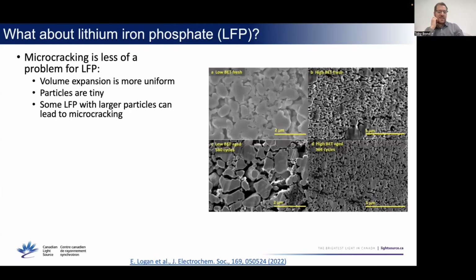Okay, and then one last slide, because I mentioned I would come back to lithium iron phosphate. Is microcracking a problem in LFP? Not as much is kind of the short answer. This is because that volume expansion I mentioned still happens, but it's more uniform, and the particles in LFP are tiny. This is some research by a lab mate of mine, Eric Logan, who looked at microcracking in LFP.